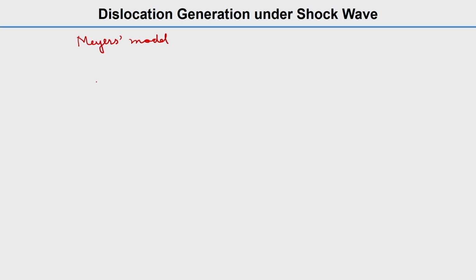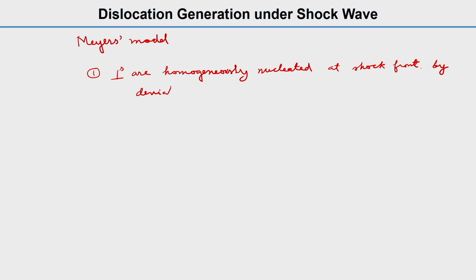Meyers' model: what are the essential features? It says that dislocations are homogeneously nucleated at the shock front. When I say at the shock front, it can be very close to the shock front as well, and by deviatory stresses. This deviatory stress is set up by uniaxial strain, and that uniaxial strain is the characteristic of the shock waves.